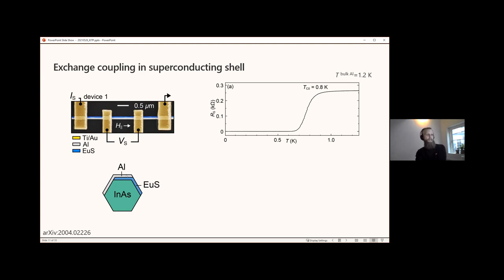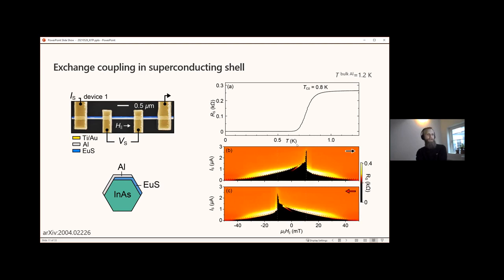And in particular, for the thin aluminum that we are using, we would actually expect the critical temperature to be even higher, because there is an experimental finding that the critical temperature and the gap of the aluminum increase with decreasing thickness. Anyhow, the differential resistance of the shell as a function of current bias and parallel magnetic field shows the following dependence. Here, the black corresponds to the superconducting state, and the color is the resistive state.